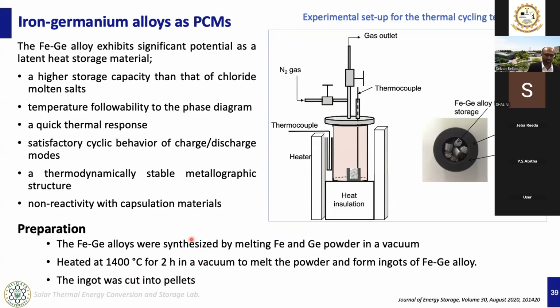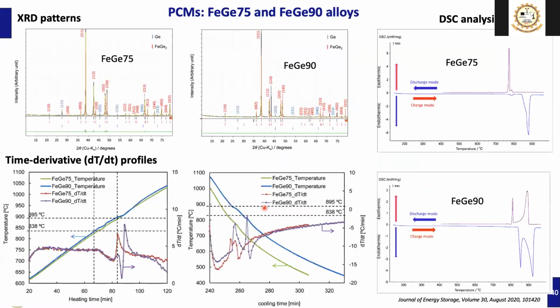To prepare these materials, the iron germanium alloys are synthesized by melting iron and germanium powder in vacuum, heated at 1400 degrees Celsius for 2 hours to melt the powder and form ingots of iron germanium alloy. These ingots are cut into pellets, and then these are all the usual procedures. We take XRD to check the XRD patterns, and we usually do DTA, dT by dt profiles, to check where the melting starts and where the melting ends, and what the latent heat of fusion is. All these details we obtained from these profiles.